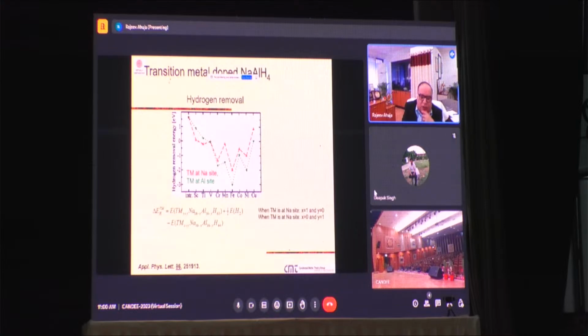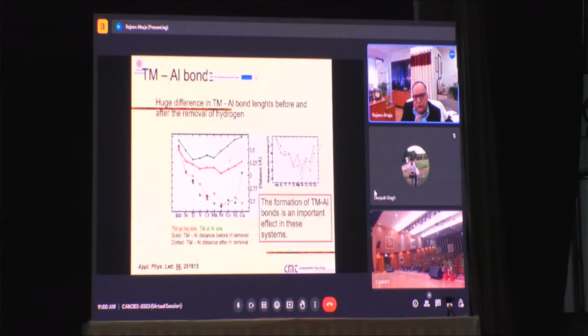And then you can ask me why iron trichloride works much better than titanium trichloride. So you can see that if you plot the bond distances, it's lower for the iron. If you look at this picture, my left hand side and right hand side, you compare this picture. For the hydrogen removal energy, you can see it is lowest, and here the bond distance for iron is also lowest. So if we can reduce these bond distances further down, we can design a new catalyst that will be even better than iron trichloride. So iron is cheaper compared to titanium. So it's a good catalyst.